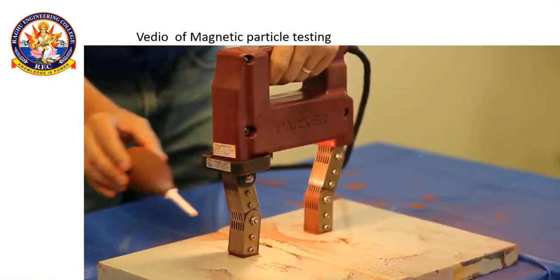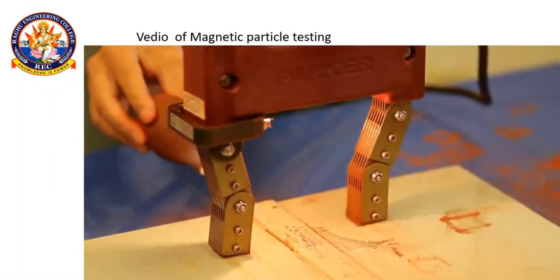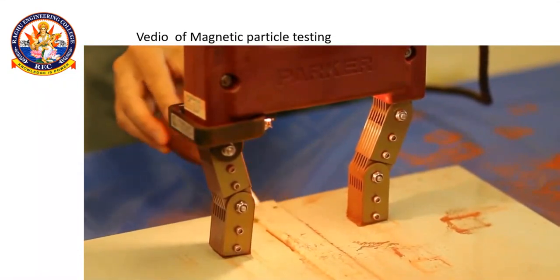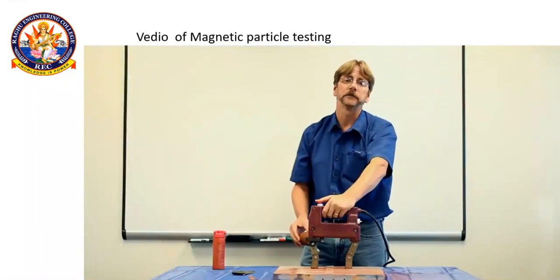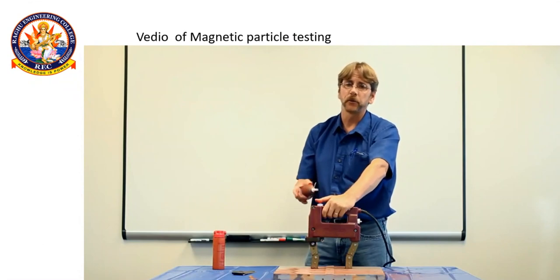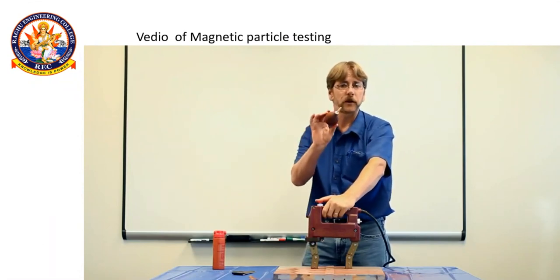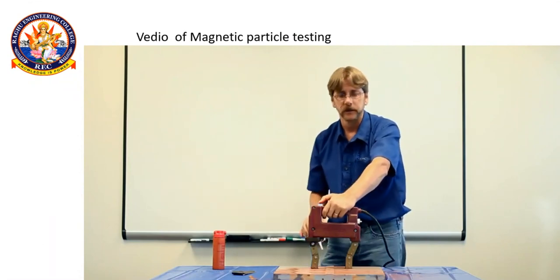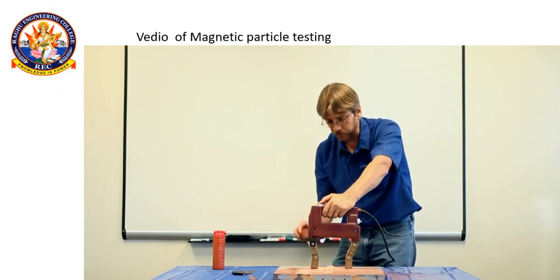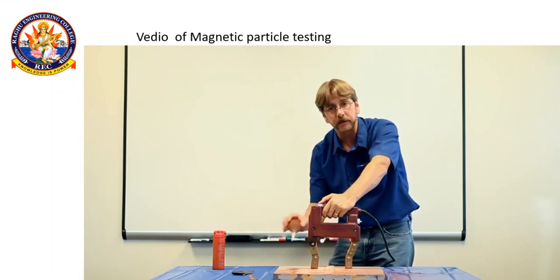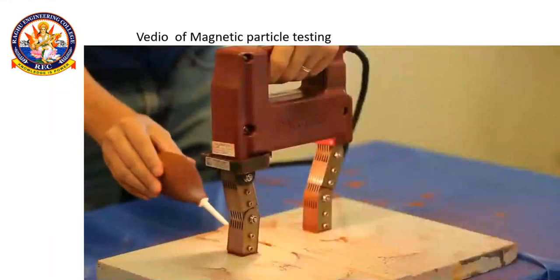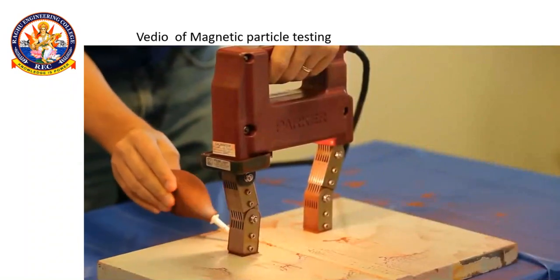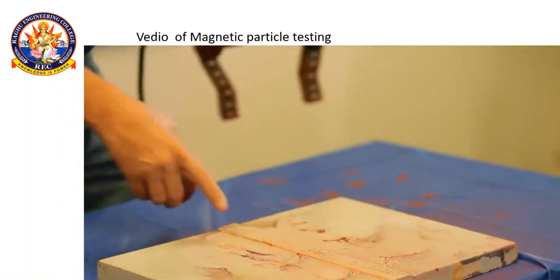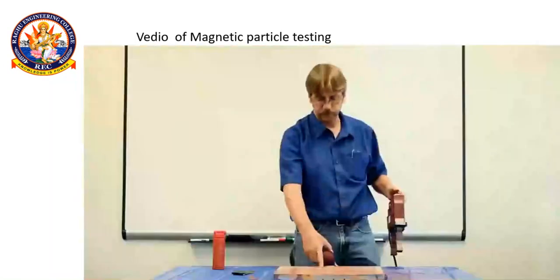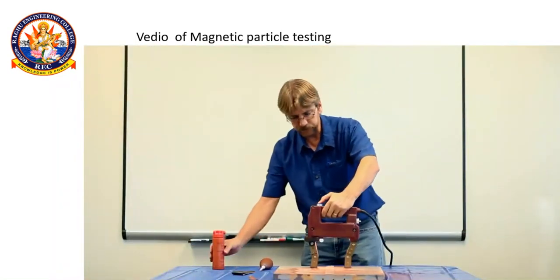See, there is one line even after blowing: that ferrous powder is attracted at that area because there is a magnet, a north pole and south pole. It means in between the two poles, that area becomes magnetized. That is a crack area, we can say.